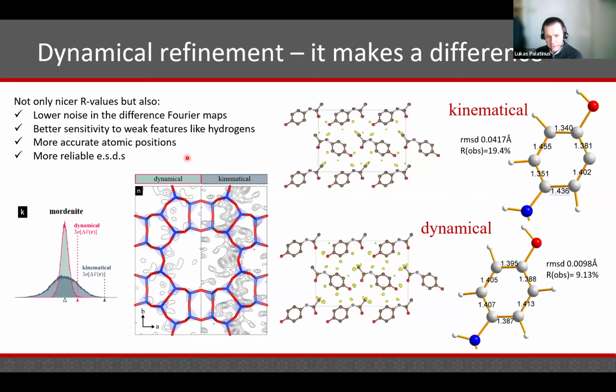So in these potential maps, in the difference potential maps, we are looking for weak signals. And of course, we want to have flat maps with no noise or as little noise as possible. And dynamical refinement really brings a large improvement, as seen in this difference potential map for mordenite, which is a zeolite. On the left, this is the difference map from dynamical refinement, and on the right from kinematical. And you see the amount of noise drops significantly when going from kinematical to dynamical refinement.